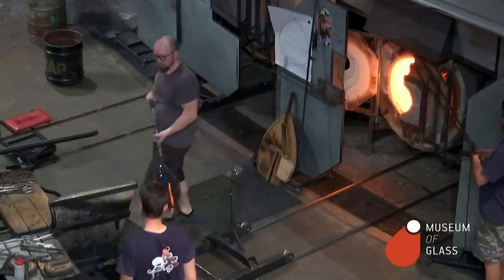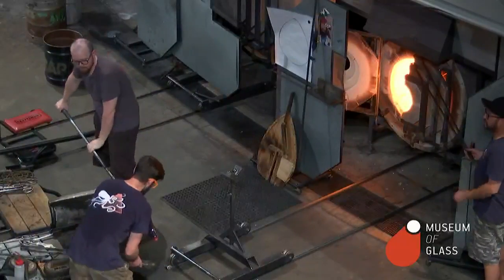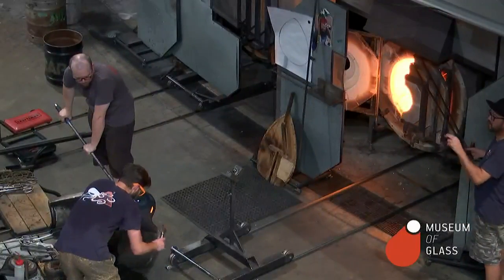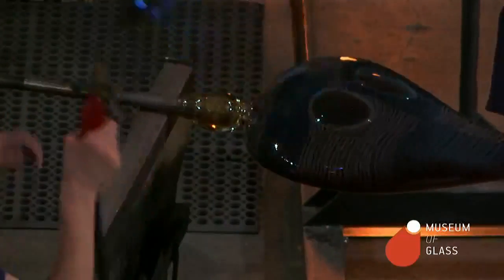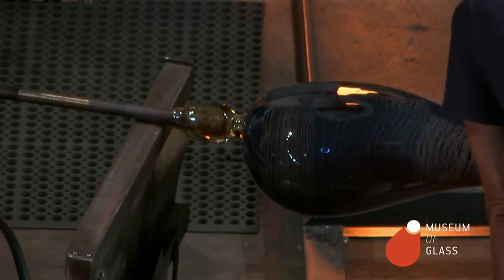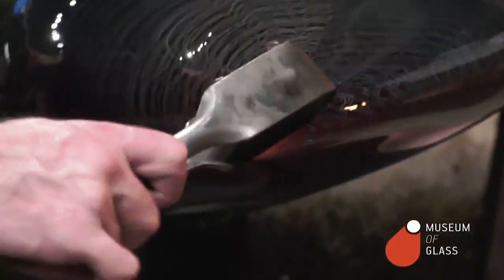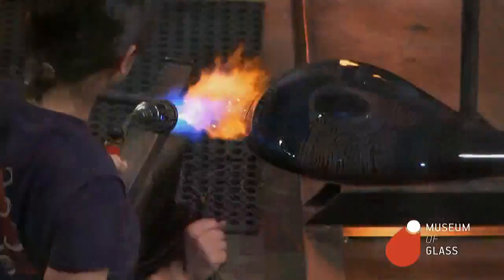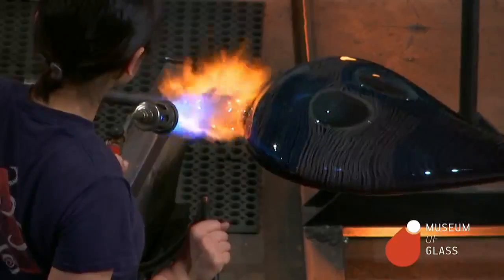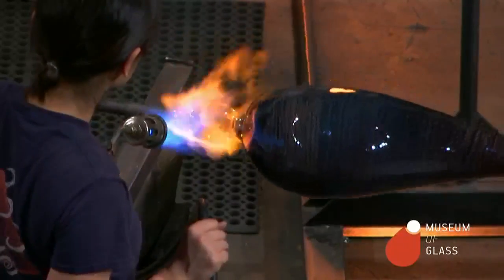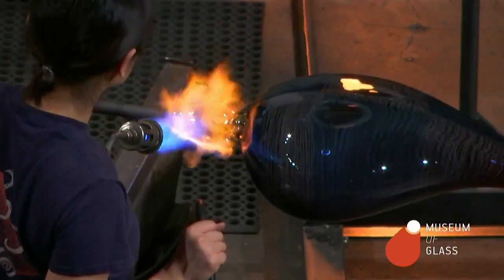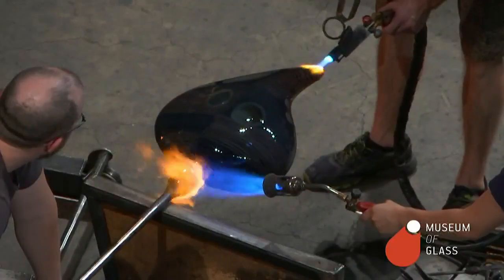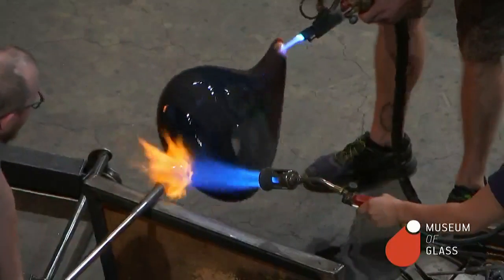So we're getting pretty close. When we finish this sculpture, we can't just set it on a table and let it cool on its own. If we did that, it would cool too quickly and unevenly, and it would shatter. So we're going to take the sculpture off the metal rod and place it in an oven called the annealing oven, where it'll be cooled slowly overnight.